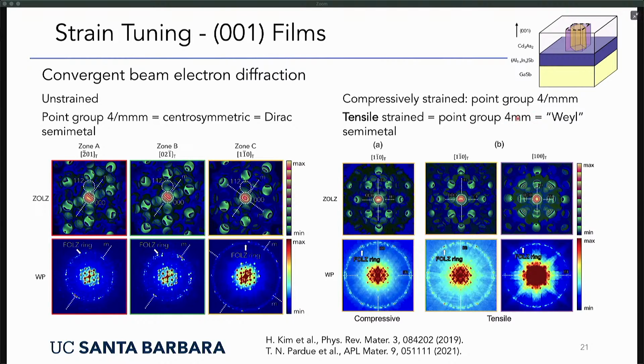This shows the surprising result that tensile strained films lose the inversion symmetry. Compressively strained films along the 001 direction do not lose the inversion symmetry. This was an unexpected result. What that means is that the unstrained material is already pretty close. The energy between these two structures, with and without inversion symmetry, is very close.